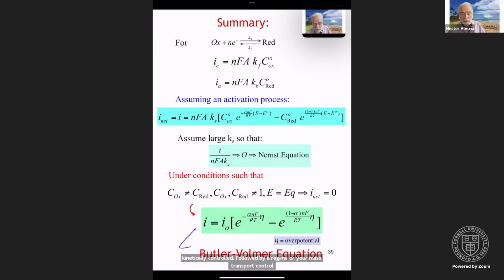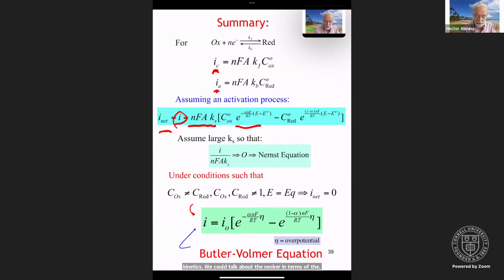And so just to take a step back and look at where we are, we started with a very simple process. Ox plus n electrons goes to red, we have K forward and K back. We could define a cathodic and an anodic current, assuming an activation process, basically Arrhenius-like kinetics. We could talk about the net current in terms of the exchange current density, nFAKs, the difference between the reductive and oxidative processes. When we assume large Ks, we basically obtain the Nernst equation. Under conditions where we are not at equilibrium, we could basically get the Butler-Volmer expression.